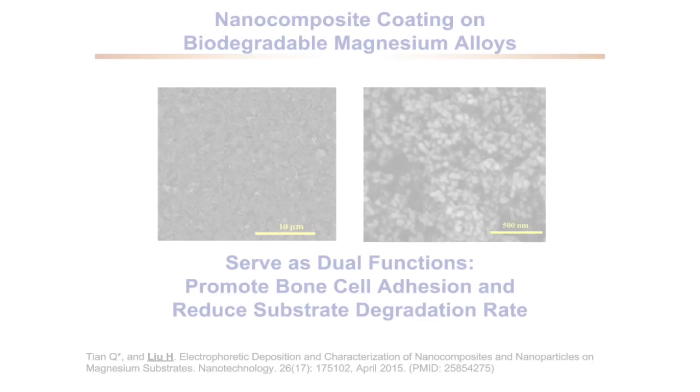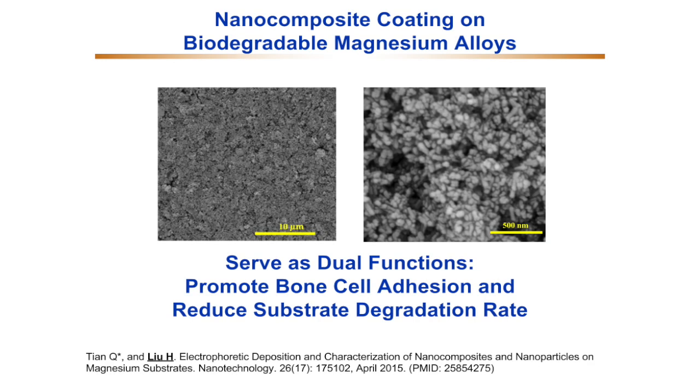Although ceramic-polymer nanocomposites provide many attractive and promising properties for bone regeneration, their mechanical strength is still not adequate for many load-bearing applications. Therefore, we applied this nanocomposite material as a coating on biodegradable magnesium alloys.